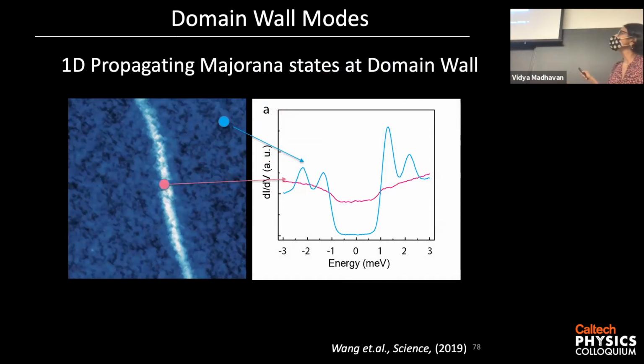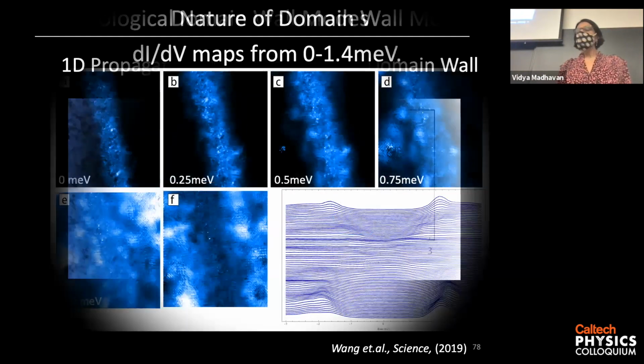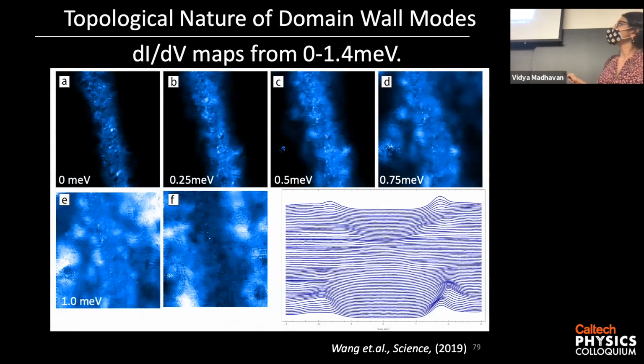So we can do more. What we can do is we can actually ask, how are these things localized near this region? And what theory tells you is that if you look at the states right at zero, they should be pretty well localized. But as you get away from zero, the states should get broader and broader in real space until they merge into the bulk. So here are maps as a function of energy.